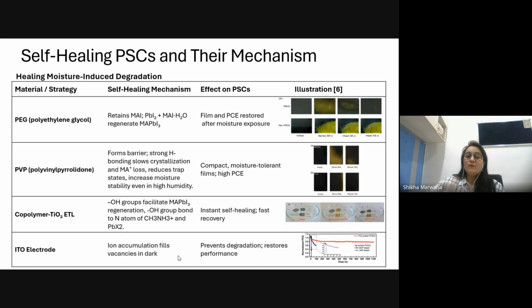Another we have is the ITO electrode. Instead of using any other electrode, if we make use of an ITO electrode, again, electrodes are necessary if we want to have the charge collected at the final end. If there is any ion accumulation when we are using ITO at the perovskite interface, then in the dark, this ion accumulation starts to fill the vacancies. If there had been any vacancies because of the moisture, they start to be filled in the dark. So it prevents the degradation.